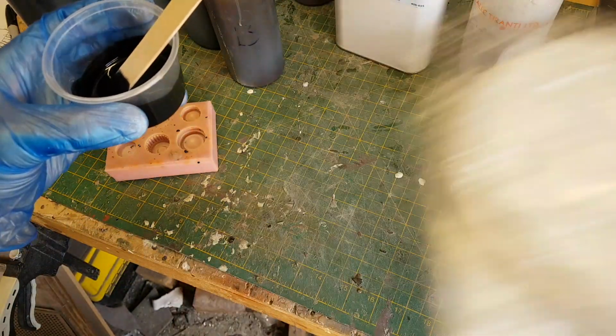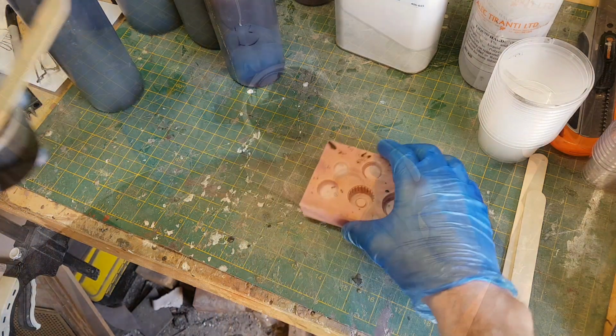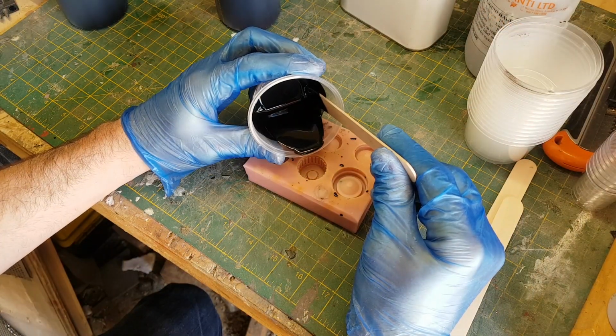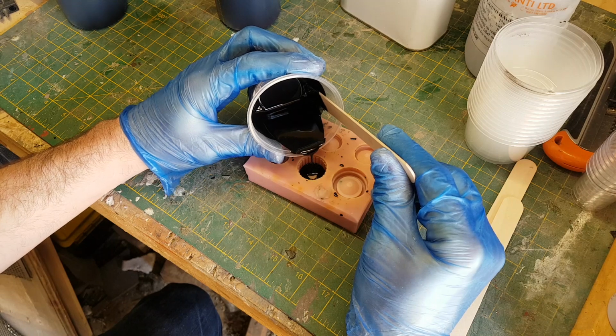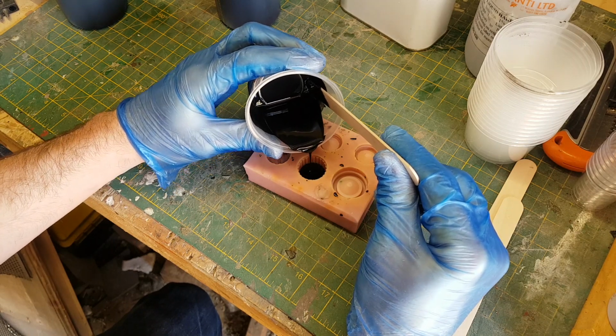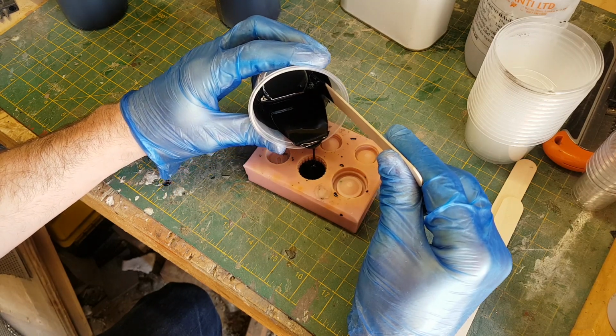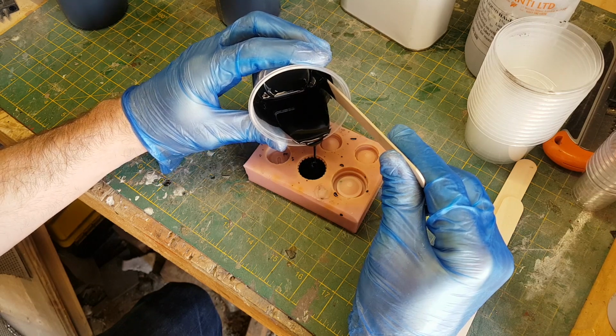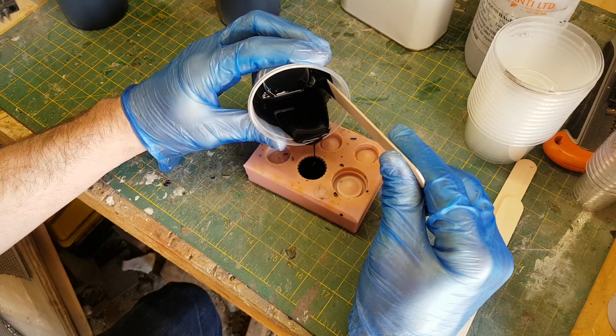Let's get the scales out of the way. And yeah, you just pour it into the mold. Now, I generally try and do this quite slowly, simply so air doesn't get trapped in the mold. I've generally found that isn't much of a problem, but occasionally if you just dump it in there, it can sometimes trap air. So best to do this slowly.